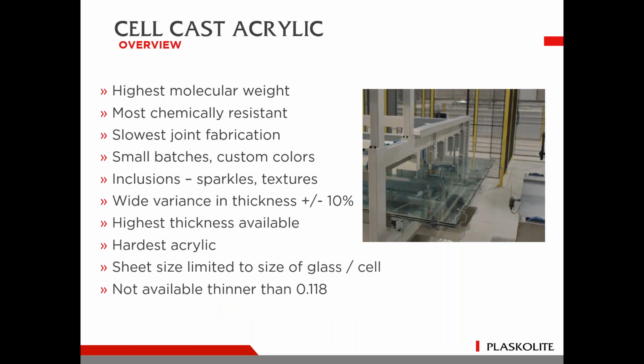So the cell cast acrylic, again, is liquid monomer poured into a big mold. As you can see in the picture on the right, those are two big glass plates. That is what the mold consists of. You put it in there, you press it together and generate some heat, and it cures into a sheet. It is the highest molecular weight sheet of the acrylic group, and it is the most chemically resistant one. Some of the things you're going to find that may be good or bad is that there's going to be a wide variety of thickness across the sheet. If you can imagine pouring it into a mold and pushing them together to generate a sheet, that can generate some variances and pressure points. So the thickness may vary across the sheet. You can make some of the thickest sheet available, though, with cell cast acrylic sheet. It is the hardest sheet available as well.